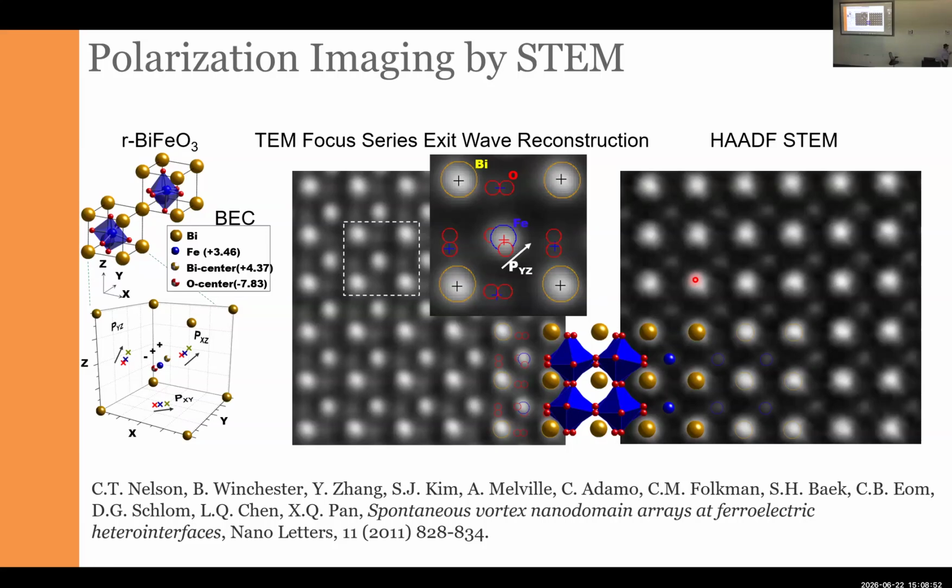And this is the case where, the first time I saw the papers coming out of Jia's group in 2009, 2010, my question was like, okay, I didn't realize that we can do it this way. Because it turns out that if you want to analyze the physical order parameter fields out of the high quality STEM data, what you can do is just take the image, fit the position of each column by a certain function like a Gaussian, take the position of the center of this Gaussian and say that this center of the Gaussian is just the position of the atoms.